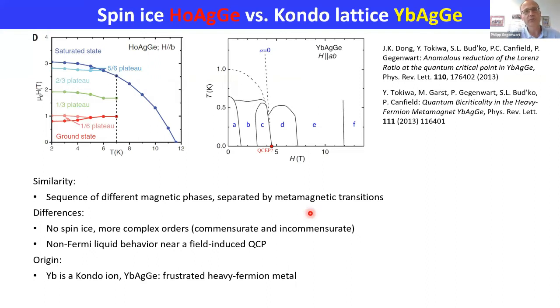So it is natural to compare the holmium-silver-germanium with the ytterbium-silver-germanium, which was actually studied quite some while ago. About 10 years ago, we studied it in collaboration with Volker Fiedler's group and found that it has an interesting phase diagram, which also consists of several magnetic states, which are separated by metamagnetic transitions. So there is a sequence of different magnetic phases, but there are important differences to the Kagome spin ice case. Namely, none of these orders respect the Kagome spin ice rules, but it's a more complex order.